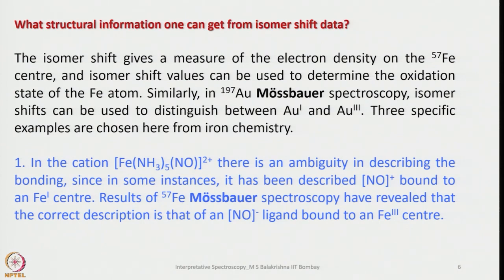Similarly, in case of 197 gold Mössbauer spectroscopy, isomer shift can be used to distinguish between gold 1 and gold 3. Three specific examples I have chosen here from iron chemistry to explain both isomer shift and also to get structural information. For example, in the cation, if you take pentaammine nitrosyl iron 2+, there is an ambiguity in describing the bonding, since in some instances, it has been described as NO plus nitrosyl cation bound to iron 1 center.